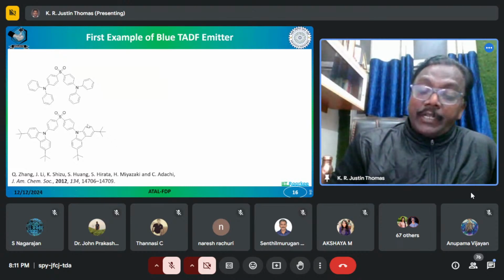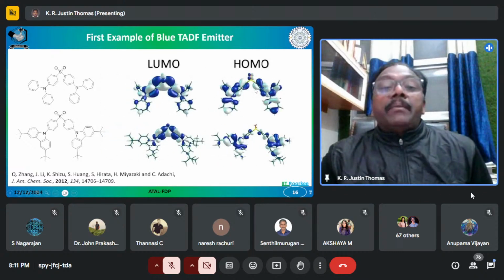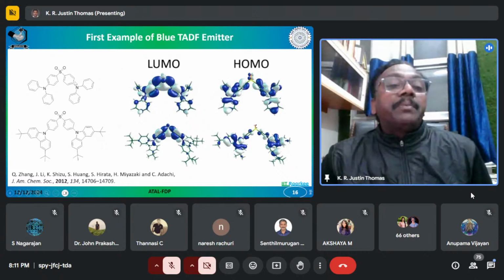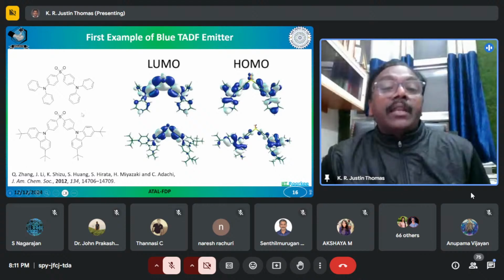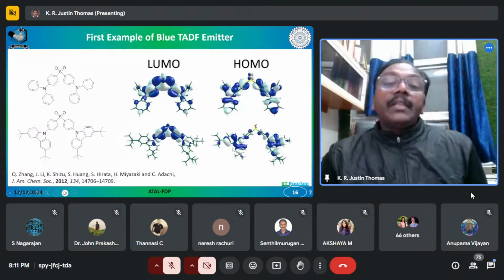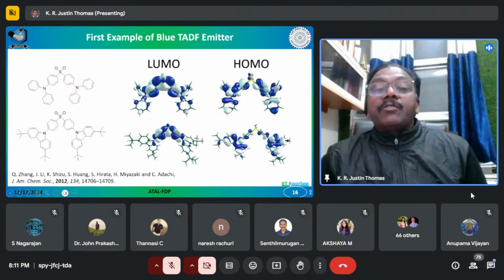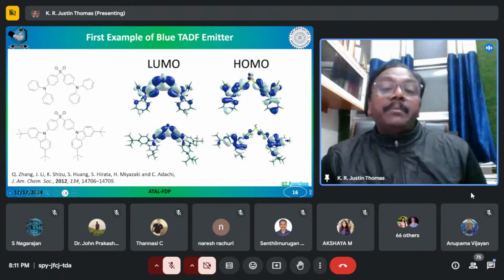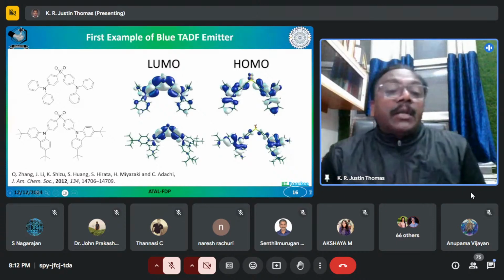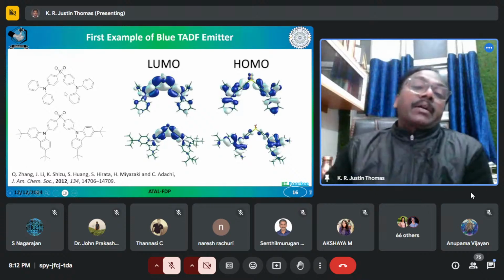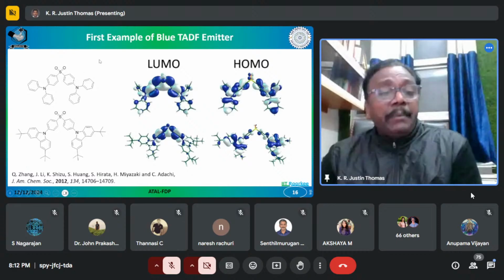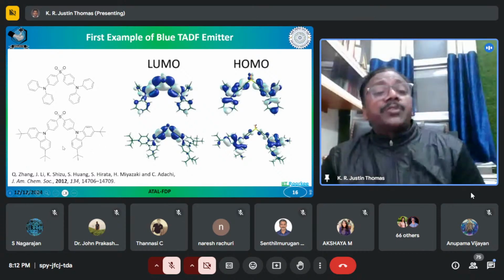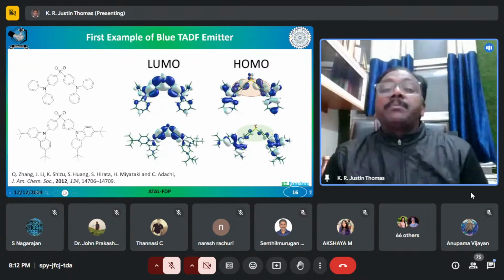And here also, when you have triphenylamine, which is shown at the top, the LUMO is mainly on this part, and the HOMO is spread on the diphenylamine unit as well as on the phenyl unit. So there is a significant overlap of HOMO and LUMO in the case of the triphenylamine derivative. But when you go to the carbazole derivative, the LUMO is very similar to the triphenylamine compound. However, the HOMO is now restricted mainly to the carbazole unit. There is little overlap between the HOMO and LUMO. So from this, one could expect that the carbazole-based compound will be TADF, and the triphenylamine-based compound will be a normal fluorescent material. That means this should be capable of harvesting triplet excitons in an LED, so it should give a higher efficiency in an LED. Okay, that is what is being found.